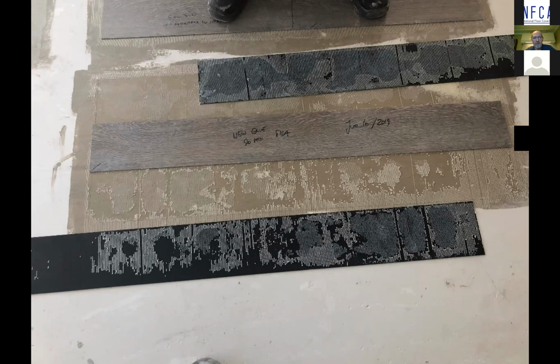And what we want to see is adhesive that is stuck to the substrate and adhesive that's stuck to the backing of the material, and that we've got proper transfer into it. Like, you look at here, we're not tearing any of the substrate up. So the primer's holding very, very well. The adhesion was incredible, but we're also getting transfer to both the backing and the substrate. So it's called a cohesive break in here. So this is what we managed to get in this particular job.